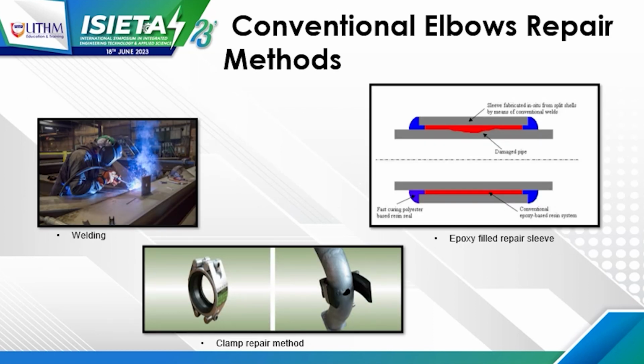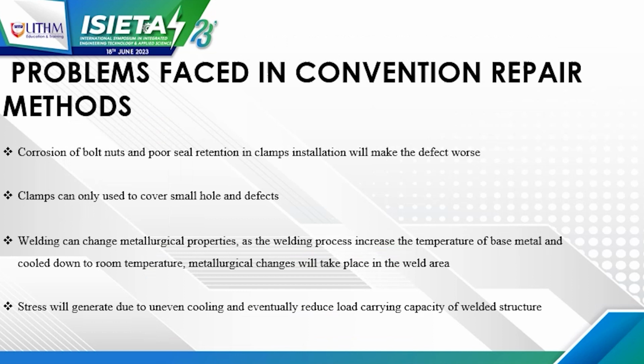There are other conventional elbow repair methods such as welding, epoxy fill, repair sleeve, and clamp repair methods. But the downside of these repair methods is corrosion of bolts and nuts, and of the seal retention clamp, and also welding, due to the increase in temperature of the base metal, which then cools to room temperature very quickly. Uneven cooling will reduce the load carrying capacity of the welded structure. That means the welded part will not be strong enough and will change the strength of the material.